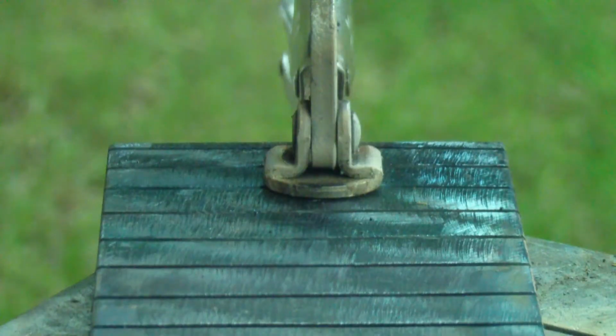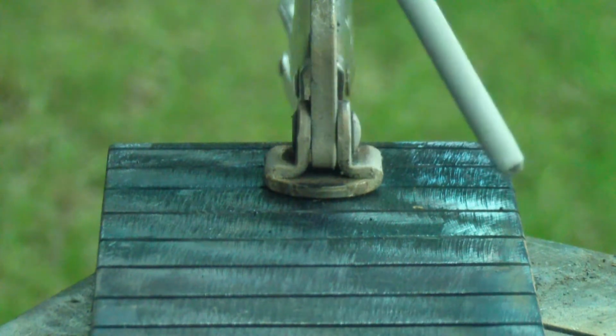Arc welding is the process in which an electrical arc is formed between the work and the end of the welding rod. When the electrical arc starts, it will immediately create a temperature of about 6,000 to 10,000 degrees Fahrenheit. This very high temperature will melt both the base metal and the end of the welding rod. The core metal of the welding rod at the contact point of the arc is melted into tiny molten droplets, and these molten droplets will be carried across the arc and mixed with the molten base metal.